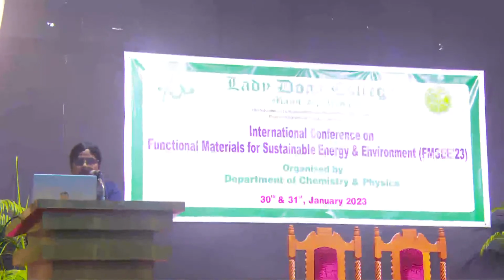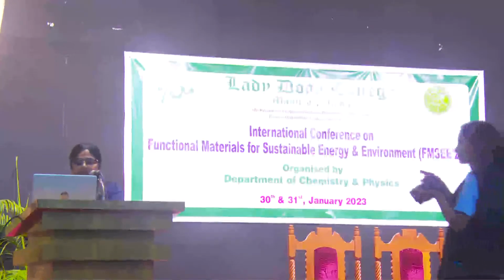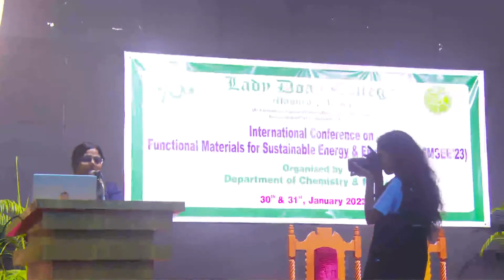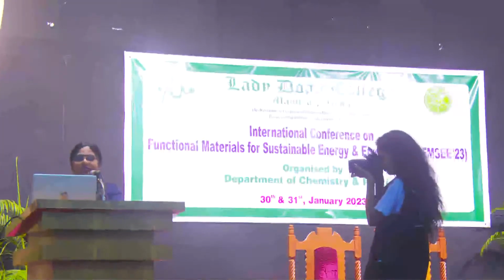After that, we also made 2 other samples where we dope it with cobalt chloride and copper acetate separately. And then we place it in a muffle furnace for about 4 hours from 400 to 500 degrees Celsius. That was the optimum temperature that we used. So this is a one-step process and it does not require any kind of chemical activating agent.